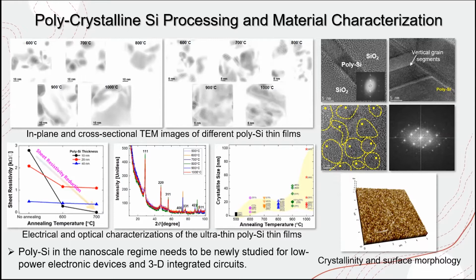But the polysilicon research in the past is different from what I am pursuing these days, because the device structure is scaled down to below 100 nanometers, and grains reaching a few or some tens of micrometers have shrunk to 10 to 20 nanometers. In these circumstances, the material properties become totally different, although we can commonly call them polysilicon. So mobility and electrical and optical characteristics should be found again, assuming that we are dealing with a totally new material.